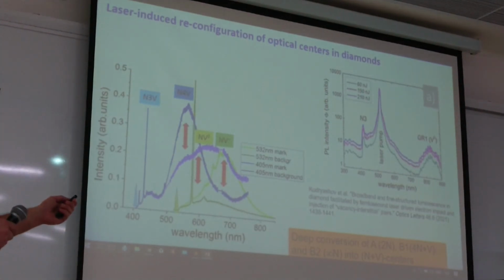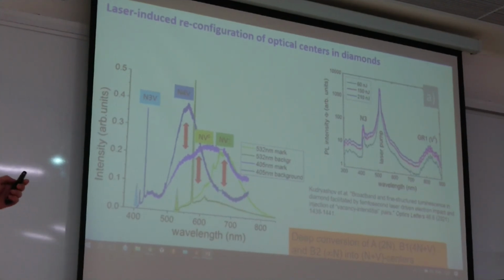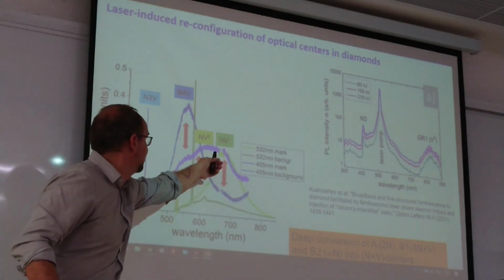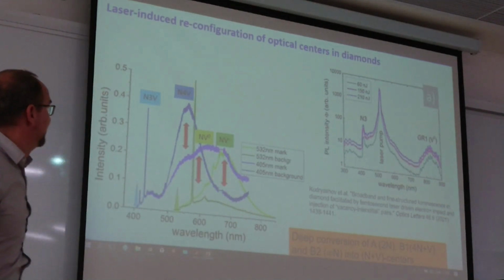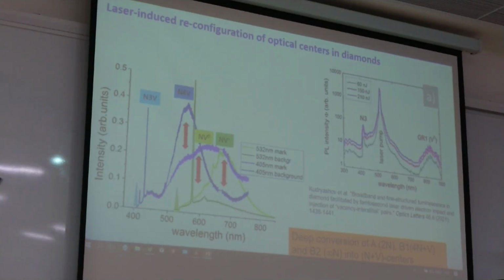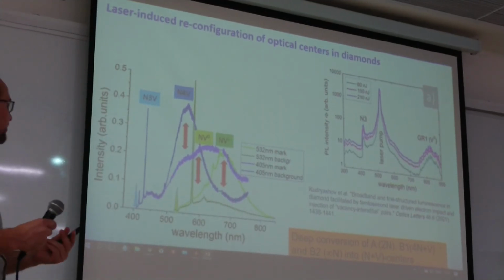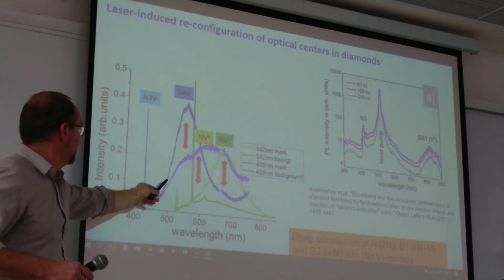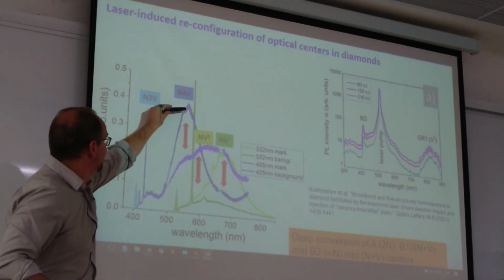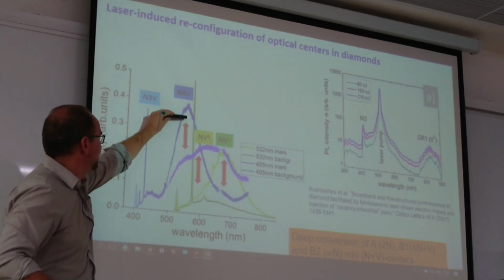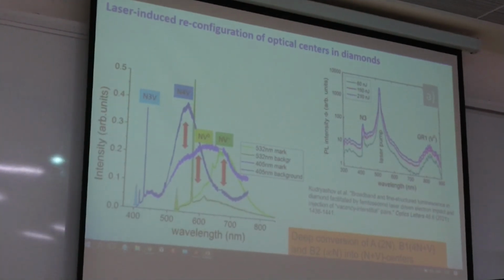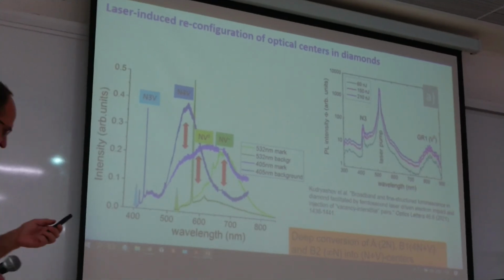We can see that what's going on in this case is just changing spectra from dark green to light green. So this kind of luminescence is increasing, corresponding to these centers, to the increase in the marked region. And similarly, we can see that these centers, their luminescence is decreasing. So there is conversion of one center to other centers here.